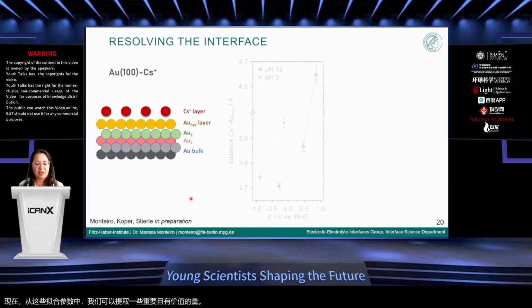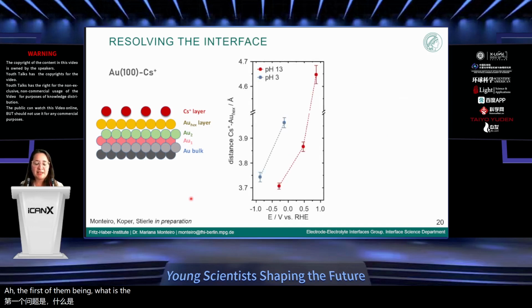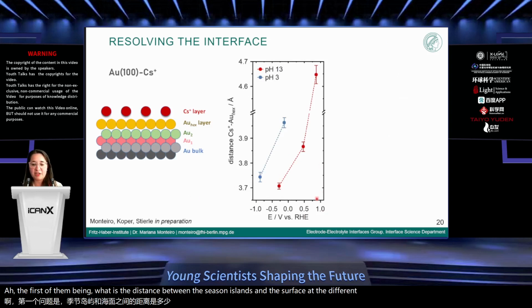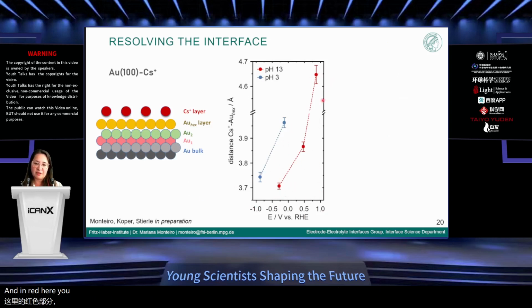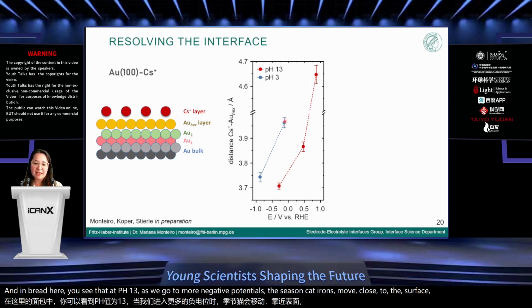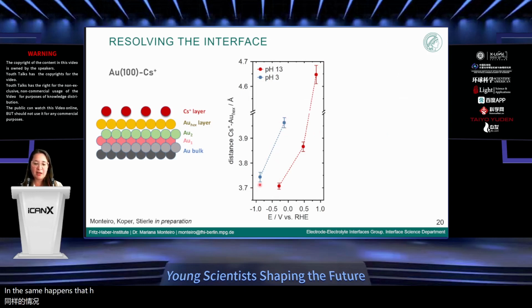The first of them being what is the distance between the cesium ions and the surface at the different pH and the different potentials. And in red here, you see that at pH 13, as we go to more negative potentials, the cesium cations move close to the surface. And the same happens at pH 3. However, if we would now, let's say, shift these curves